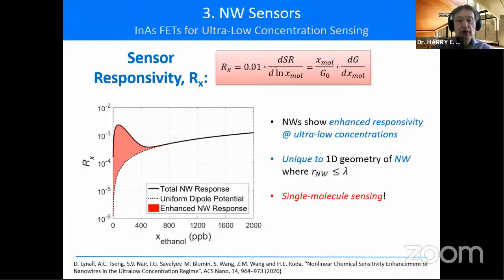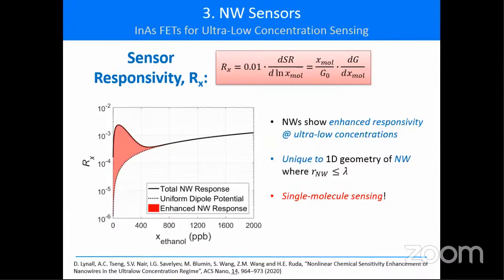Well, in the full model, which I just described, you see that there's a peak at the very small concentrations, and that peak is due to the nanowire geometry, and particularly that very weak screening which you get, which is controlling that screening, and then the onset of the single scatterer type of regime. And that's where there's actually a massive enhancement, which you don't get in any other structure, and that's where these nanowire systems can be extremely useful.